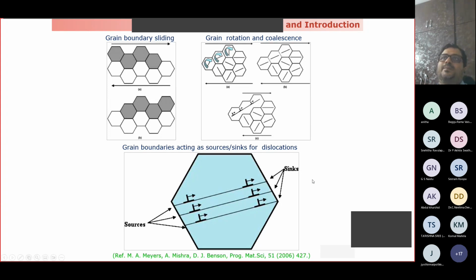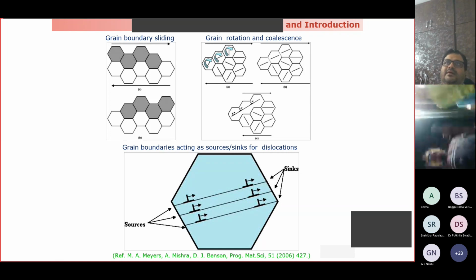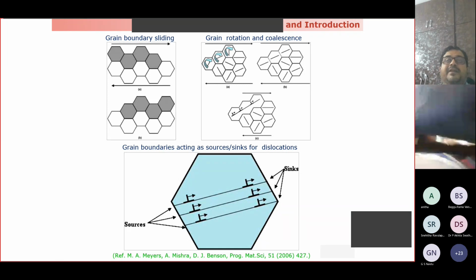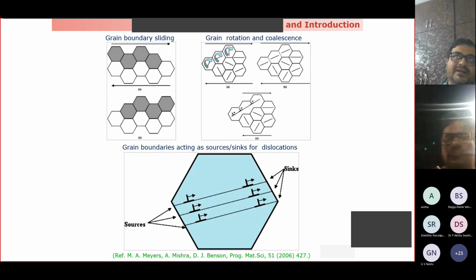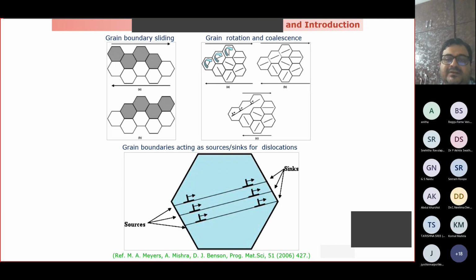So as a result, the moment you apply stress, you can generate a lot of lattice defects. It can be a missing row of atoms, it can be a missing plane of atoms, or it can be any other lattice defect. And here dislocations are shown. So they travel across the grain and get absorbed on the other side, because you also have a space on the other side. So on one side, grain boundaries act as sources of the generation of lattice defects. On the other side, they act as sinks for the lattice defects. And these are all observed in molecular dynamic simulations.